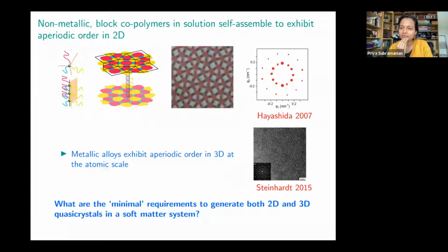It's because soft matter experiments with tri-block copolymers, which were done by Hayashida, showed that if you were to crystallize them in the third direction, they would be uniform, they were columnar. But in the two-dimensional plane on the surface, this is the top view of that experiment, overlaid with a scanning electron microscope image in grayscale, you have this decoration marked out in red lines. And you can see that this decoration is really rectangles and equilateral triangles.